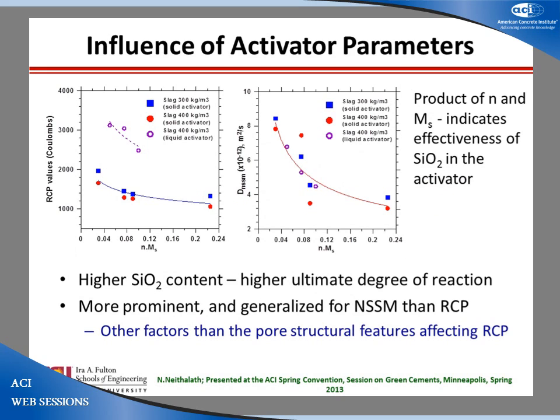One thing to note, because we have two different activator parameters: one is the N value, which is the sodium oxide content, and the other is the MS, which is the silica to sodium oxide ratio. If you multiply those, you effectively get the silica content in the activator. So you can nicely trend those non-steady state migration values at 28 and 56 days to the silica content in the activator, irrespective of the sodium oxide content, for the range that we have studied. It's an easy way to start looking at what kind of values you need for a target non-steady state migration value, something to be used as a guide before you start designing your mix.